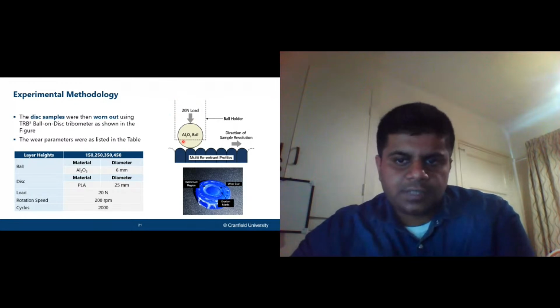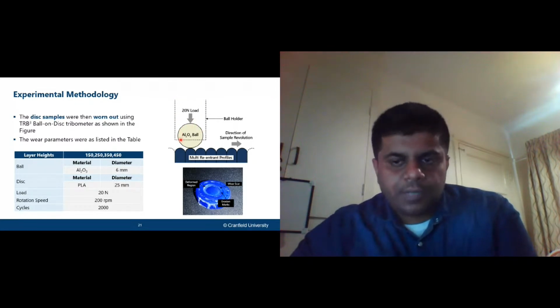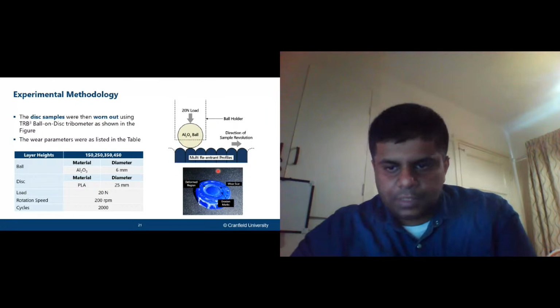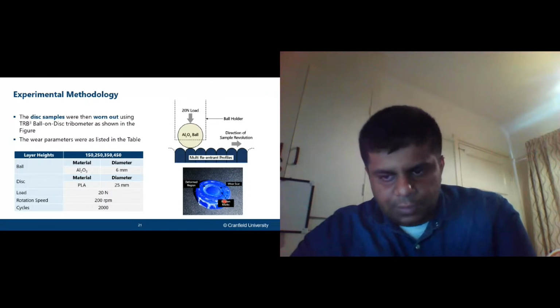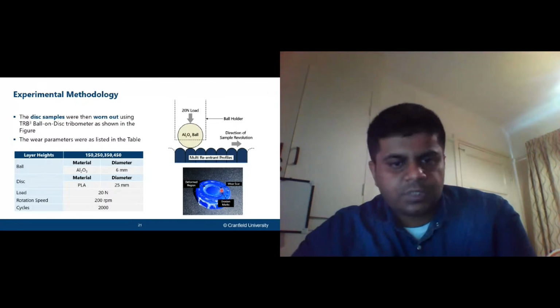The ball we're using is ceramic, which is common for tribology of plastic specimens, and this is how the specimen was after the investigation. You see 2 wear scars over here. They are for different investigations. For repetition, we actually conducted tests on both the outside and the inside edge. So you see 2 scars over here, but this is how the wear scar looks like. You see some deformed region as well because of heat generated during the wear process, and you see some erosion marks as well because the material chipped off from this particular region.